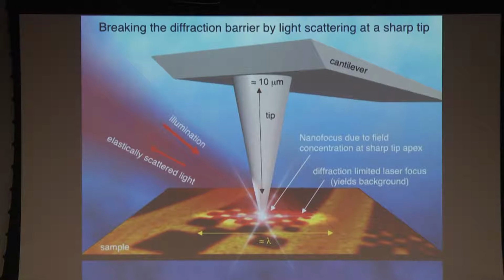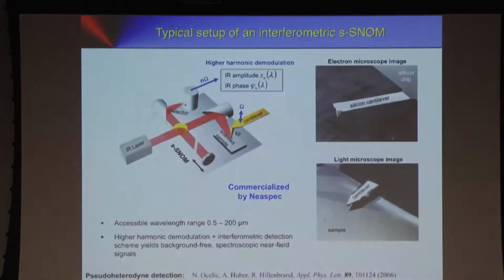And here the problem starts, and we solved this problem over many years. I will show you on the next slide how, but first the problem. You can imagine that the volume from which the light scattering occurs is much, much smaller than all the light that is illuminating the tip shaft and the sample here. So we have a huge amount of background. And that was one of the major problems in the very beginning, to extract the light that is scattered due to this nanofocus here.